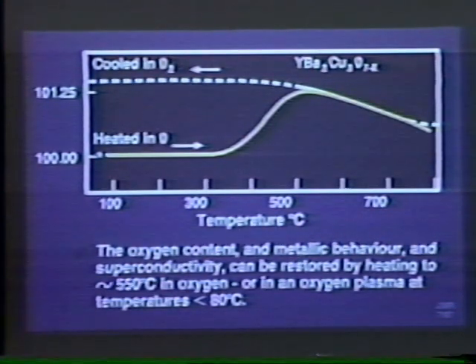Therefore, the oxygen content and metallic behavior and superconductivity can all be restored by heating to about 550 degrees in oxygen. Or as we've shown at Bellcore recently, you can actually do that at much lower temperatures by exposing the material to an oxygen plasma. In fact, all we used was a little barrel reactor that's conventionally used in semiconductor processing. Now, that work of ours was done on bulk samples and needs to be demonstrated much more conclusively on films.